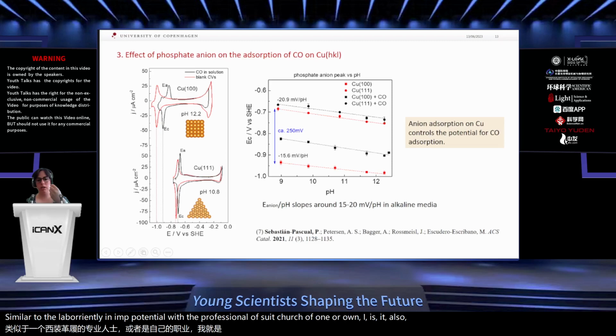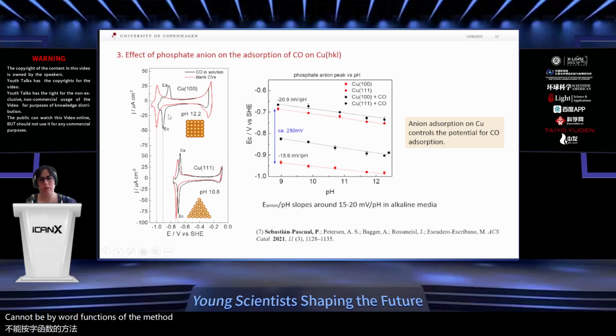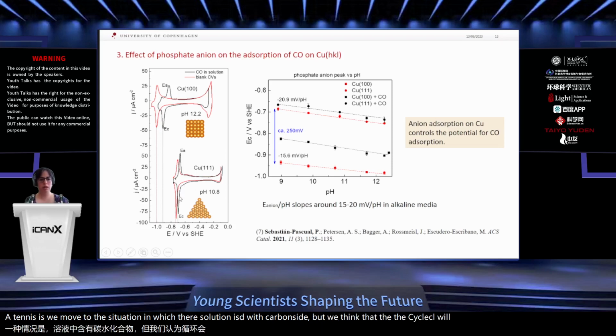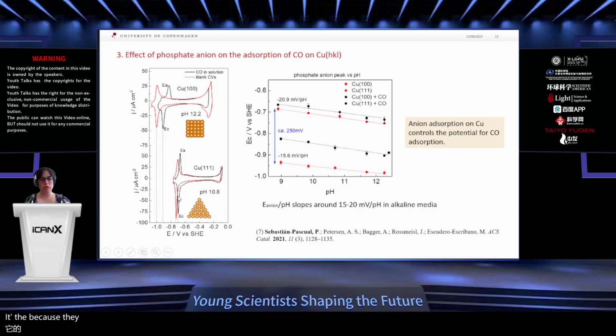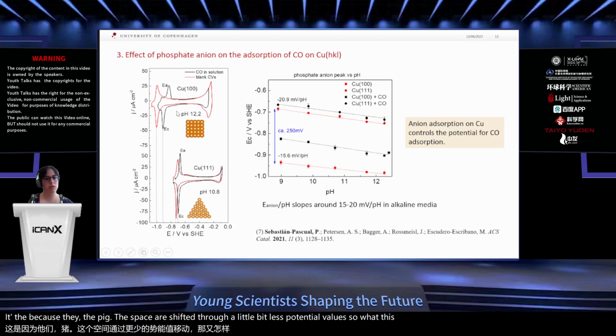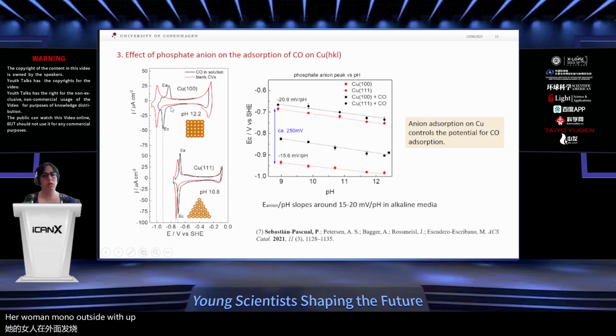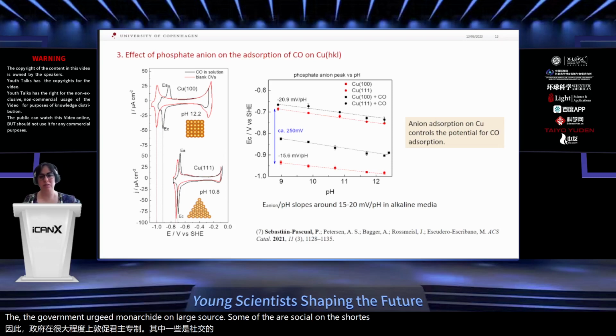So the adsorption strength of the anions, or the energetics of this anion adsorption desorption, cannot be explained by work functions of the metal. But then if we move to the situation in which the solution is saturated with carbon monoxide, what we see in the cyclic voltammetry, now the black line, is that the peaks are shifted to slightly less negative potential values. So what is happening here is that the carbon monoxide, which adsorbs quickly on the surface, is adsorbing at the potential in which the anion is about to desorb. So it means that the carbon monoxide cannot be adsorbed on the surface unless the anion is able to be desorbed.